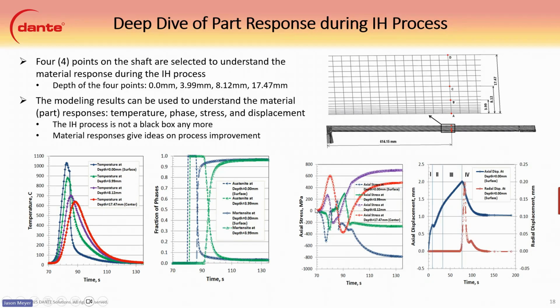The part in the core, just for contrast here, goes quickly to tension and then back down to compression as the martensite transformation happens, and then it goes back to tension in the core. And you can see these are pretty high values for the tension here.